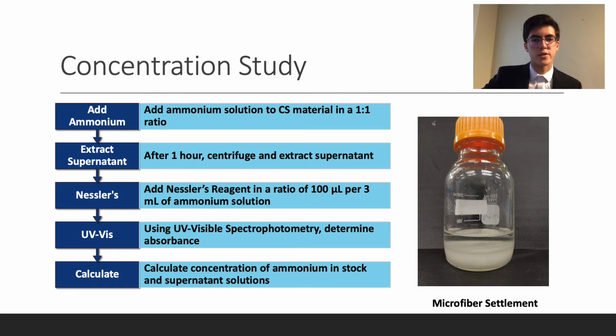Once the materials were characterized, a concentration study was attempted on all 3 of the materials. Essentially, what the study involved is the addition of ammonium in a 1-to-1 ratio to each respective CS material. Following a 1-hour period, the supernatant was extracted, Nessler's reagent was added in order to visualize ammonium within the supernatant, UV visible spectrophotometry was attempted in order to calculate the concentration of ammonium in the supernatant compared to the concentration that you started with initially. And using that difference, we could tell how efficacious each material was in removing ammonium from solution.